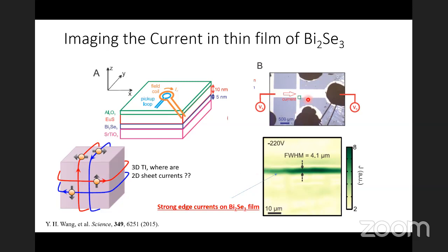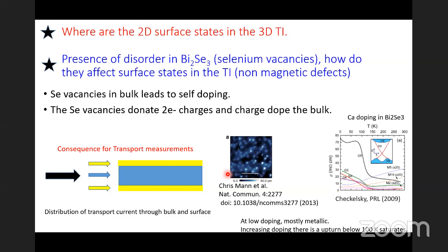What they saw was that at the edge of these films, there are strong edge currents. These are not like 2D currents. These are very strong edge currents. At the edge of these films you have strong currents, but as you go inside the film, you don't see a sheet of uniform 2D current; it is all concentrated along the edges. So these look almost like 1D current channels flowing at the edge of this film, and they don't look like 2D uniform sheets of current. This was one question which was puzzling us: if it is a 3D topological insulator, you should have a 2D uniform sheet of current. Where has this sheet gone? These are the questions that we will try to address: where are the 2D surface states in a 3D topological insulator?